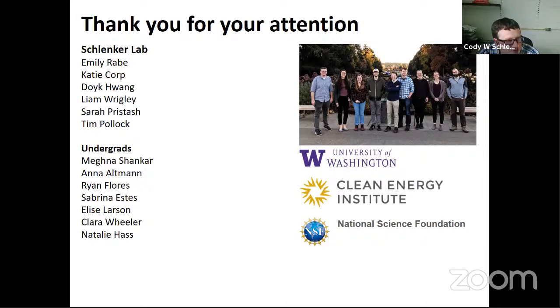At least as far as we've seen, we've run up conversion experiments in solution in a totally anaerobic environment for days and days and days at a time. We don't see any degradation. There does appear to be some photothermal effects with some of our really high energy up conversion acceptors. So if you start pounding on the thing by heating it up to 60, 70 degrees while shining light on it, there seems to be some sort of photothermal activity, but with just light at room temperature, we don't seem to see anything. In films, it's much more stable. You can do up conversion in air in a film, and it doesn't seem to be a problem there. So yeah, they appear to be much more stable than any of the halogens out there.